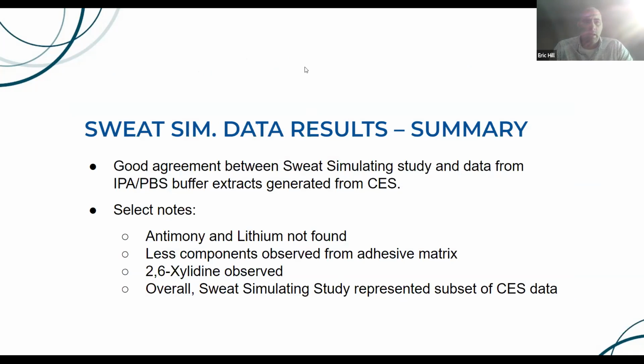From there, we went into executing the sweat simulation study. As I had reviewed previously, looking at that data, we had very good agreement between the sweat simulation study and the IPA PBS buffer extracts from the controlled extraction study. And that's really important, that we compare those profiles and verify that we have good agreement. If we had 2 profiles that were extremely different between our sweat simulation study and our controlled extraction study, that would tell us that one of those studies was not designed appropriately, and we need to go back to the drawing board and repeat some analysis and potentially change our plan. But in this case, we had very good agreement.